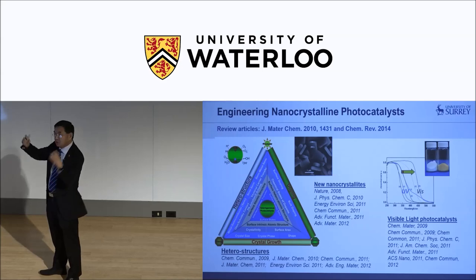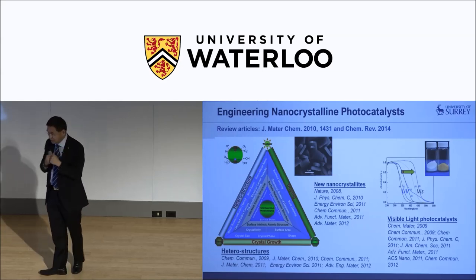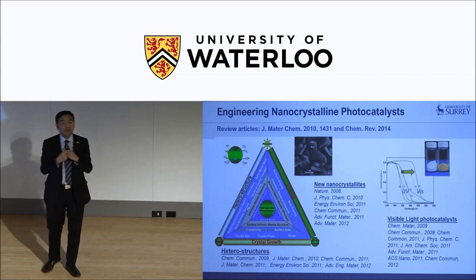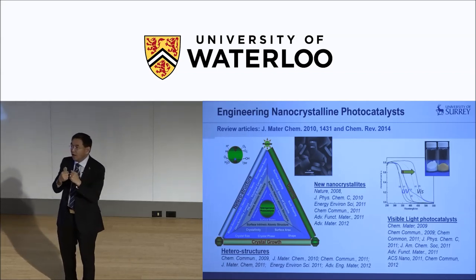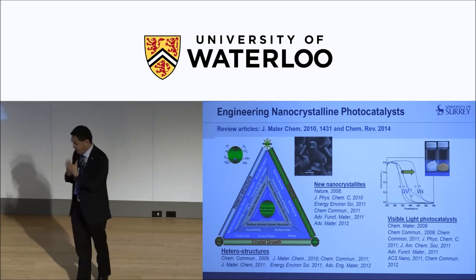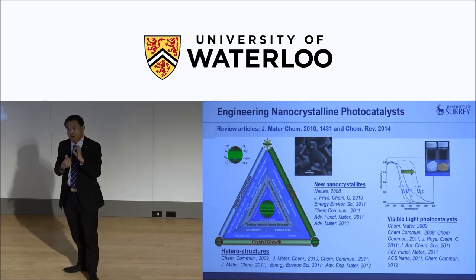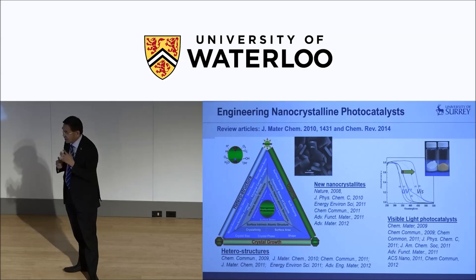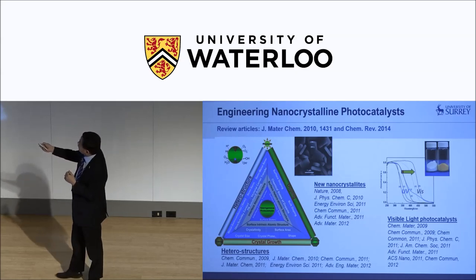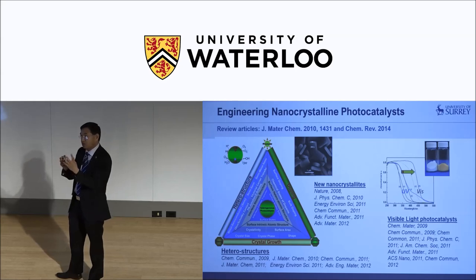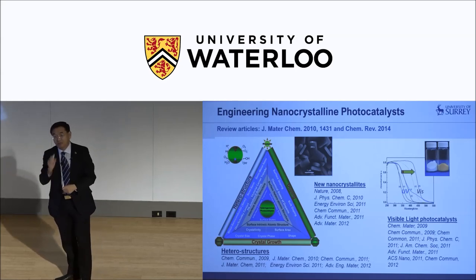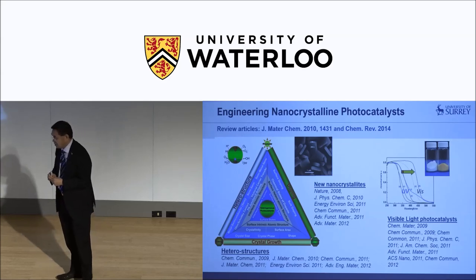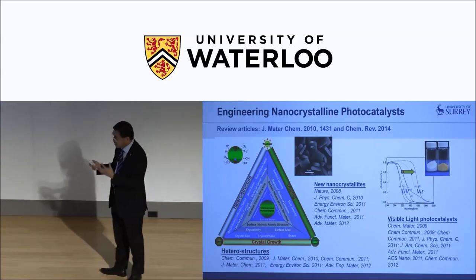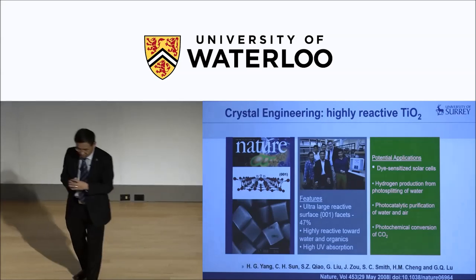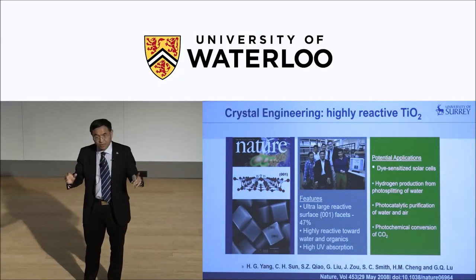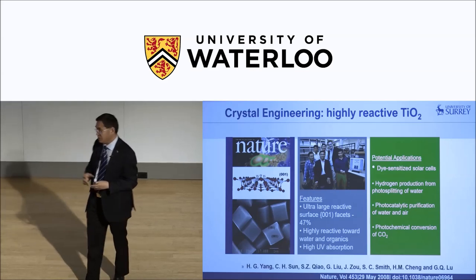Or you can do a heterostructure in two different metals or metal oxides put together that eventually will determine the interfacial properties and ultimately would be able to control the interfacial atomic structure and the carrier transfer properties. And of course, the bulk, the crystal structure and the crystal phase and crystallinity would determine the surface state. And these are the things that we did, and a lot of work. And one of the examples is to engineer the surface by a crystal engineering technique.